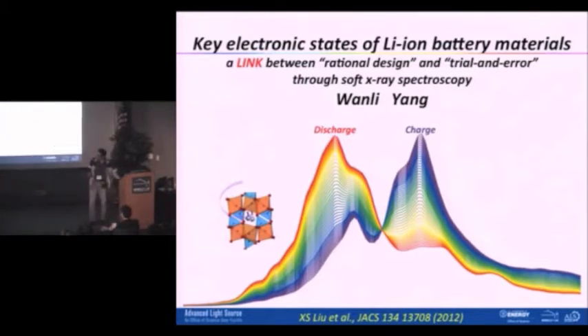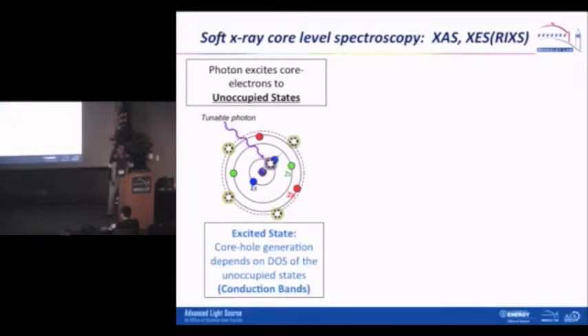I will go through very quickly what the spectroscopy is that we are really using, and then I will jump into the battery. When you shoot a soft X-ray photon onto a material, especially a low-Z material, if you tune the incident photon energy so that it matches the core level electron up to the lowest unoccupied state, or what we call the conduction band, you will get an absorption peak. This is how you detect those unoccupied conduction states.